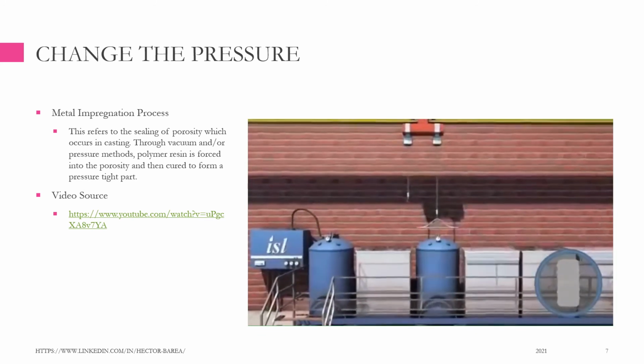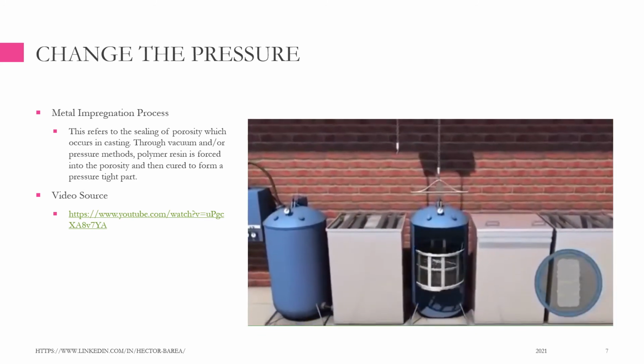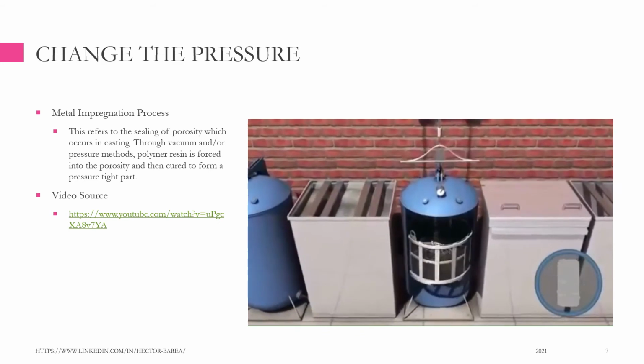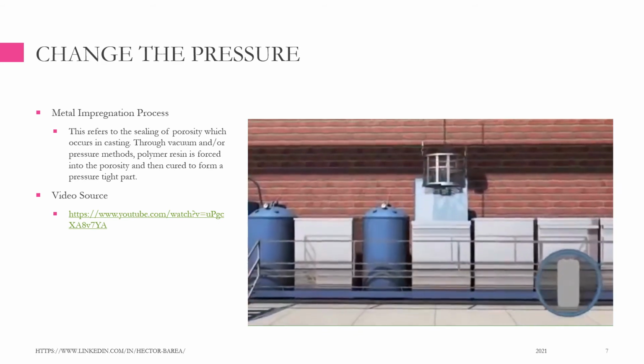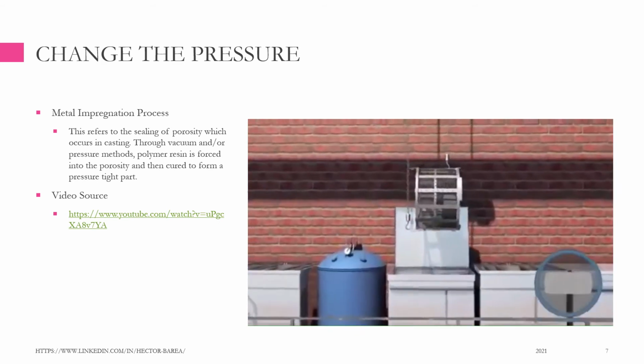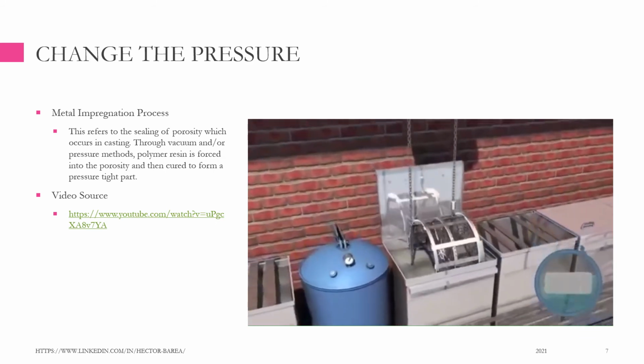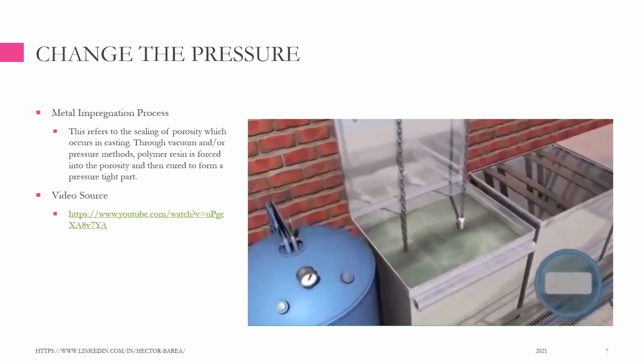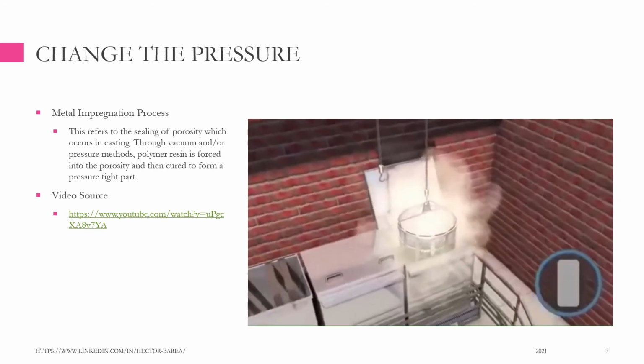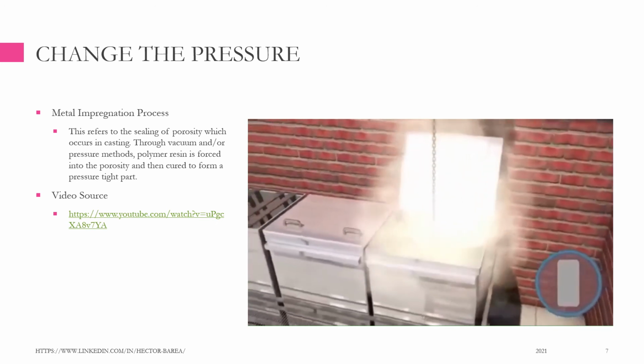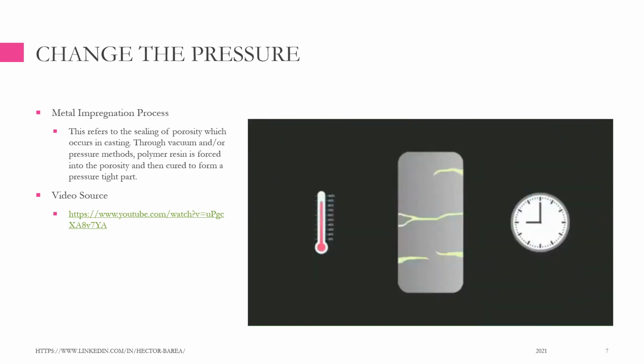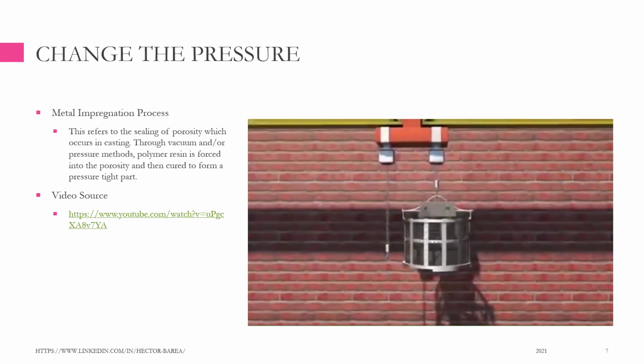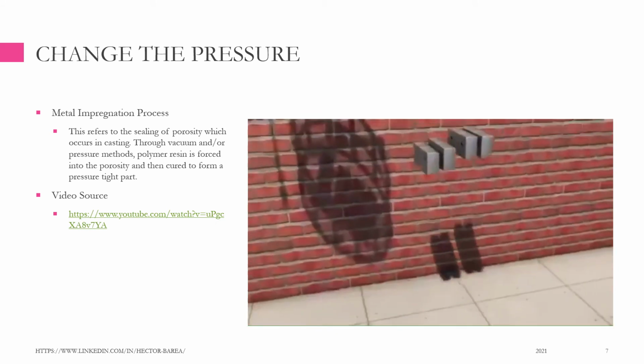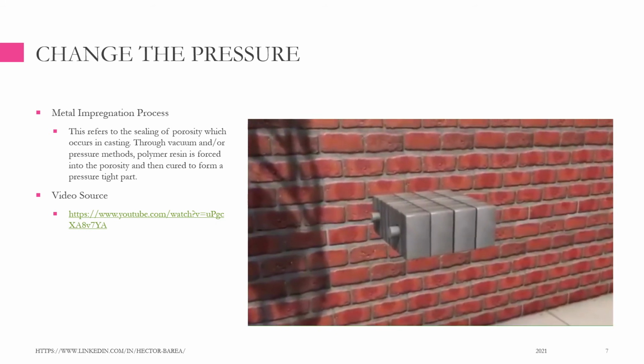The components are drained and a centrifuge cycle spins excess resin from the surface of the parts. Turning the basket and immersing in water multiple times, any remaining resin is washed off. The resin inside the pores is then cured in a hot water tank, quickly polymerizing the resin into a homogeneous material, permanently taking on the size and shape of the porosity. The finished components can now be leak tested or assembled directly.